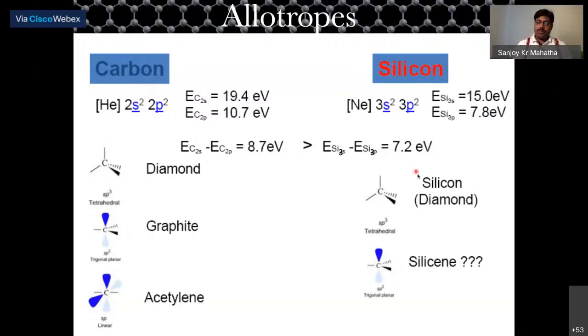But in silicon, it is mostly only diamond-structured silicon with sp3 hybridized silicon atoms. And we need to really see if this sp2 hybridized silicene or silicon is possible or not. Because if you see the energy difference of the 2s and 2p of carbon atoms, it is 8.7 electron volts in the case of carbon, whereas in silicon it is 7.2 electron volts. So the energy difference is not that much, and there might be significant overlap of s and p orbitals, and maybe the sp2 hybridization is not really possible.